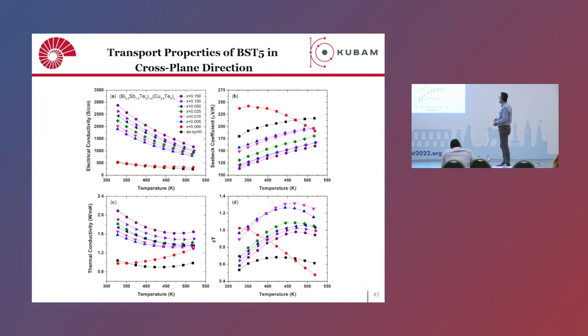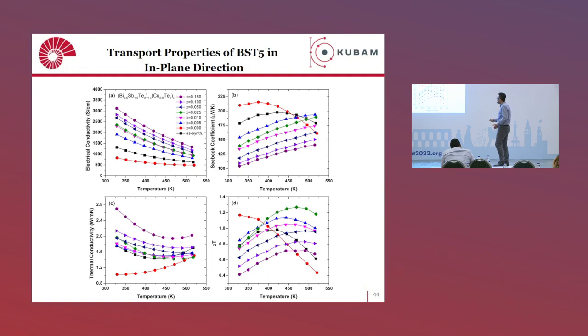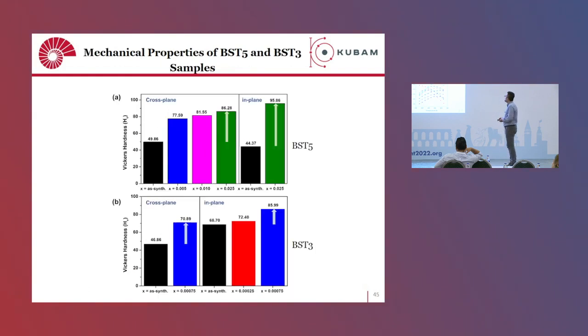So this was the cross-plane direction. We see a similar effect in the in-plane direction. The trends are the same: higher electrical conductivity, lower Seebeck, a little higher thermal conductivity. ZT is around 1.2 when 10-minute ball milling is applied, and at higher temperatures, copper telluride addition of, let's say, 0.025 gives much higher ZT values, which means that by introducing these nanoscale secondary phases, you can optimize the thermoelectric efficiency or performance of these materials.